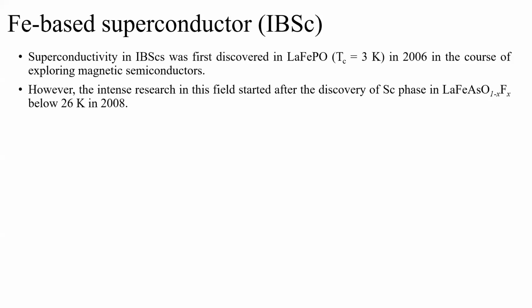Later in 2008, people found superconductivity in LaFeAsO by replacing oxygen with fluorine atoms, and they found that the Tc value went up to 26 Kelvin. And so people started looking at these compounds. Till that time, people called these compounds pnictide compounds because most of the compounds that they studied had arsenic or phosphorus in them.